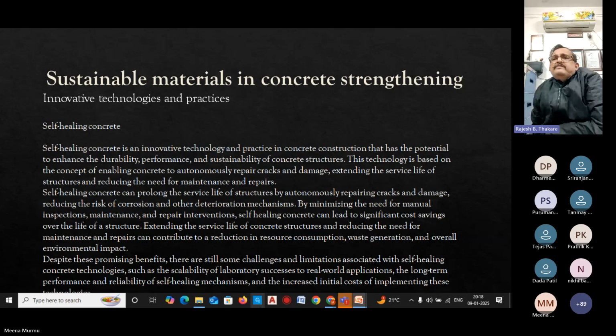So self-healing concrete can be produced by bacterial self-healing, by introducing strains of bacteria and nutrients into the concrete mixture in the mix design. When cracks are formed in the concrete, during curing or maybe in service life, the bacteria become active in the presence of moisture and begin to produce calcium carbonate, that is limestone, as a byproduct of their metabolic process. The calcium carbonate fills the cracks and restores the structural integrity of the concrete. This method has shown promising results in lab settings and has the potential to enhance the durability and sustainability of concrete structures. And further, it can also enhance the